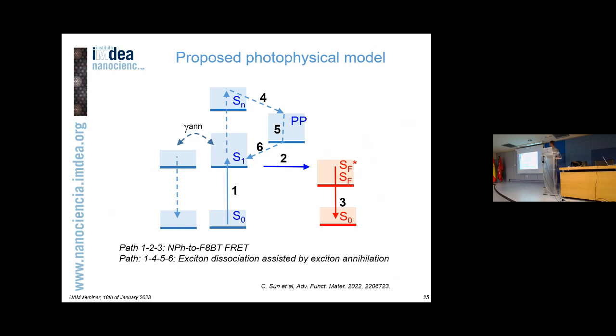Essentially, this involves photoexcitation of a singlet state, and then we have a branching. There is the possibility that this interacts with a second singlet to lead to annihilation and form polaron pairs, or the possibility to transfer efficiently the energy to F8BT. These two photophysical pathways are included in different amounts in the three different blends.